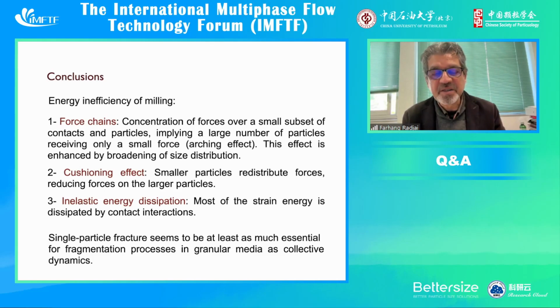Fracture energy has a limit, and so the excess energy is either dissipated by inelastic collisions and friction or carried away by the particles, and that's what we see in the restitution coefficient, which increases because we have more excess energy, let's say.